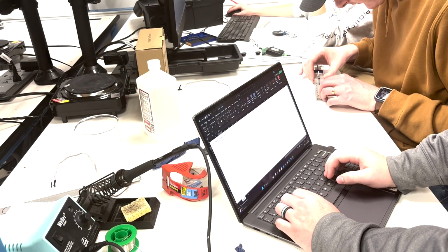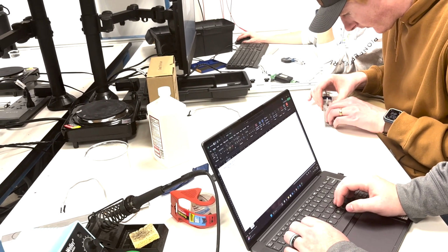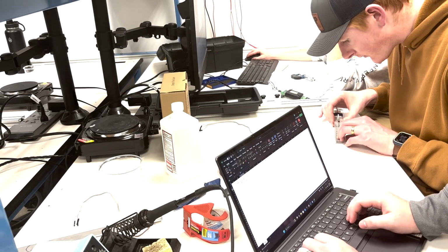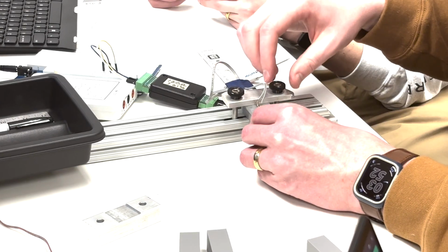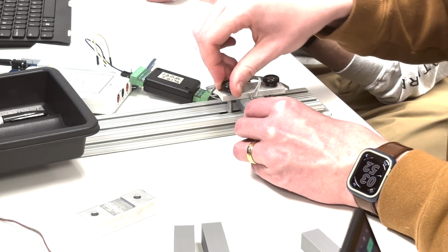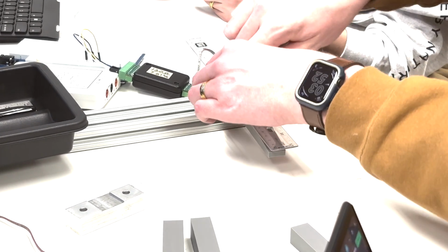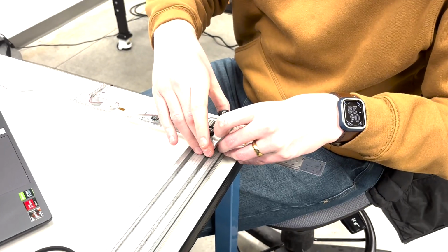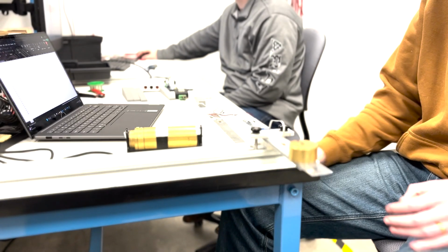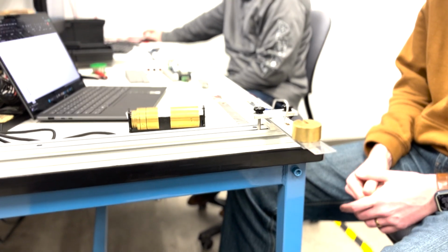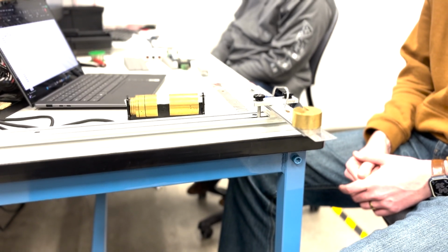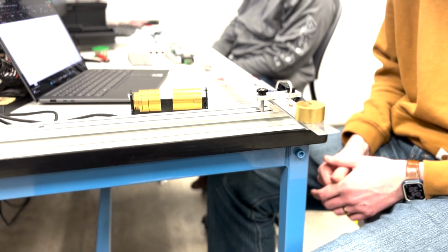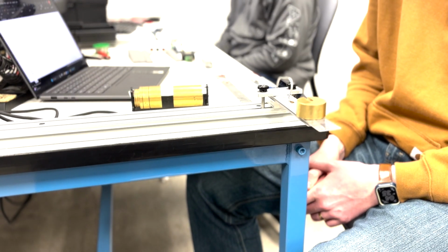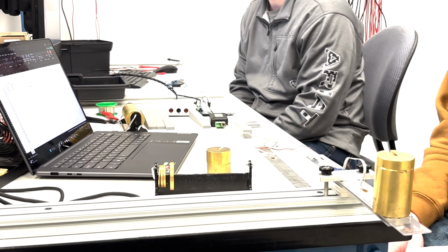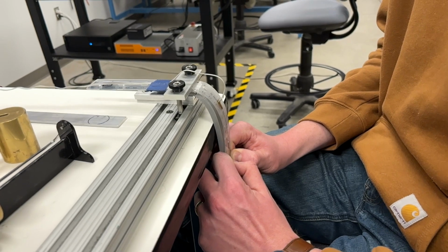Once again, the preliminary test follows the method we will use on all samples tested. A beam sample is 3D printed using PLA. The dimensions of the sample are measured and recorded using the previously used digital calipers. The sample is fixed on one end, and a known standard of masses are placed on the other side. The center of mass of the masses is placed in the same position for every test. Masses are added in 50-gram increments until the beam breaks in bending.